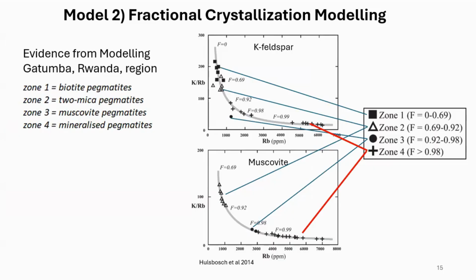So if we look at a fractional crystallization model, this happens to be a paper by Hulsbosch looking at pegmatites of Rwanda, but there are many other studies that find similar results. With K-feldspar and with muscovite, rubidium is more incompatible than in biotite. So as you fractionally crystallize K-feldspar, the K/Rb ratio goes down. As you fractionally crystallize muscovite, the K/Rb ratio goes down.